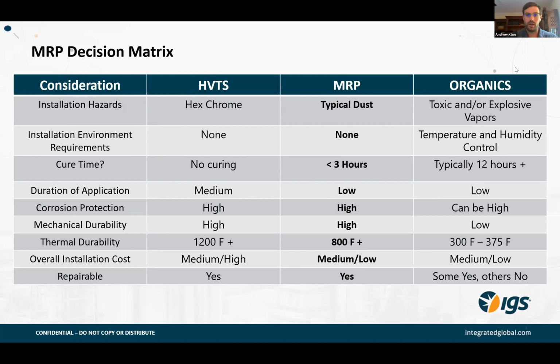So when you take all of that, and then your cure time, MRP, by the time you're done applying that second coat and you're starting to pull scaffolding, it's cured. So there's really no impact to scheduling, where organics can be 12 or more hours to cure. So taking those things into consideration, when you look at the overall cost, not just the material cost, MRP and organics are going to be in a very similar playing field, where the HVTS is going to stay on the higher side of that.